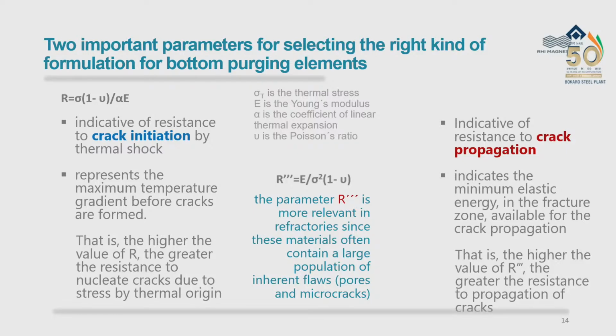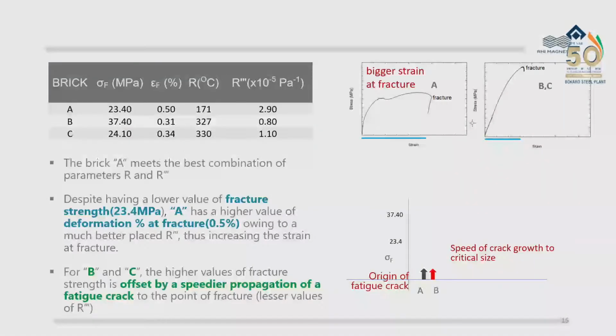I will give you an example and show it. See, I have three samples A, B, and C. A has the least fracture strength, 23.4. B is 37.4. C is 24.1. But the deformation at fracture for A is highest, 0.5. So it has got a very good value of R triple dash, 2.9.